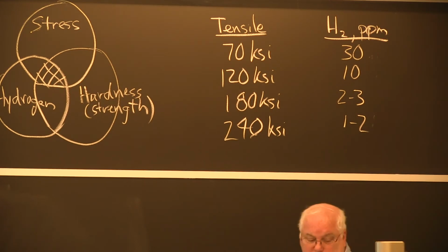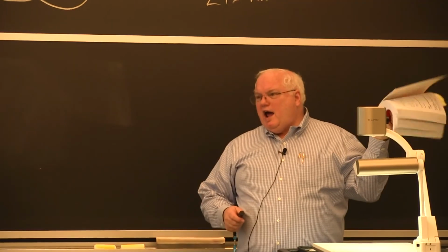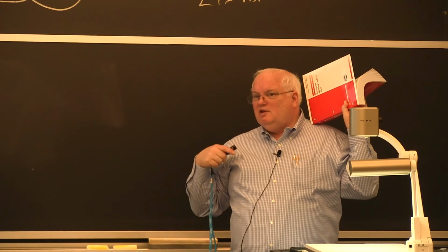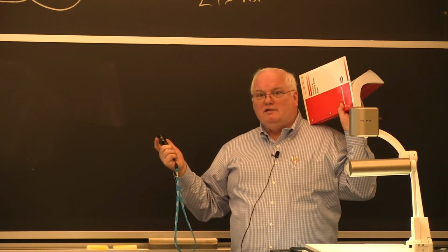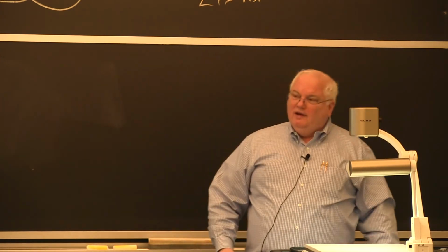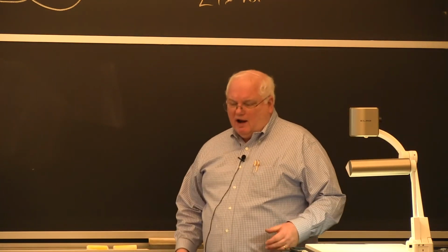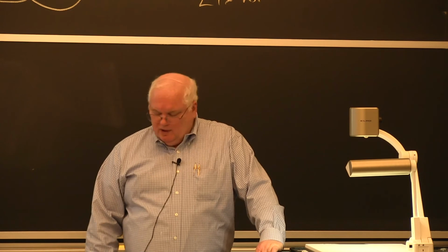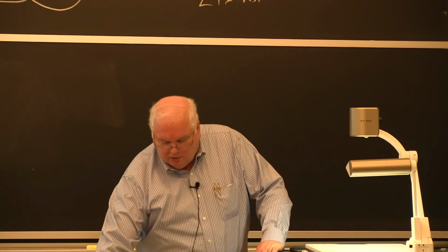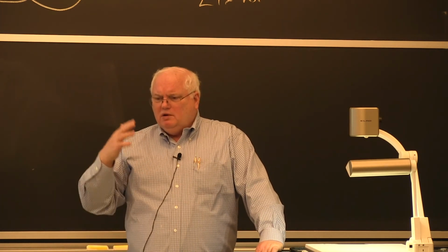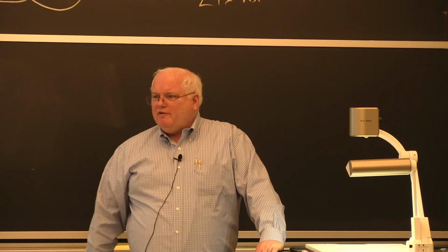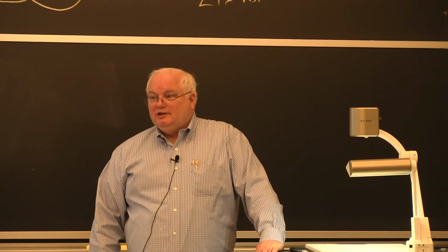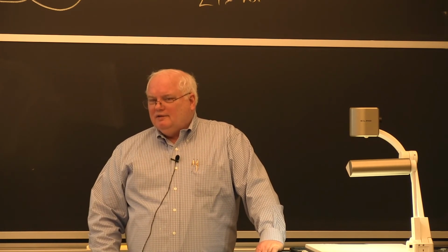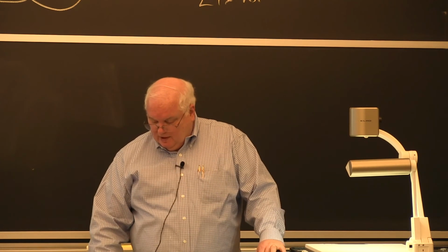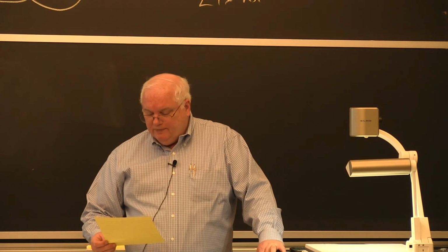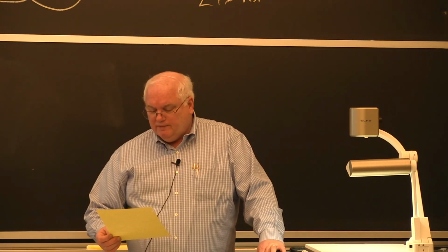This one, I could get cracking, but it requires that I wait 48 hours before I do the test. Because if I tested 1 hour later, I may not have gotten a crack yet. Okay, and then I could pass it and say no cracks, and 3 hours later there would be a crack. It's delayed cracking. I can't tell you how many times people say, "Wow, we have a crack here, but we know it wasn't hydrogen cracking because we tested it right afterwards." And I say, "Well, how soon did you test it?" "Oh, right afterwards." I said, "Well, how do you know it's not hydrogen?" "Well, we tested it. There's no crack." Well, it could have formed afterwards, okay? After the 1 hour that you did your test, you have to wait. And the U.S. Navy waits 7 days before testing for cracks.